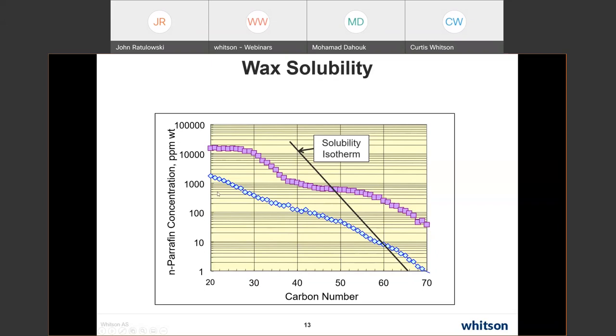Now, if I want to find the cloud point or wax appearance temperature of this fluid, you can see with this solubility curve, I'm actually below the wax appearance temperature. There are solids out here, but these are very high molecular weight normal paraffins and a very small amount of them. So the chance that I'm going to form a crystal with this amount of material large enough to see, or get a signature on a DSC large enough to see with a small amount of material, is pretty slim. So I will not get the thermodynamic phase boundary, but I will get something inside of that phase boundary. And that's true with all these measurements.